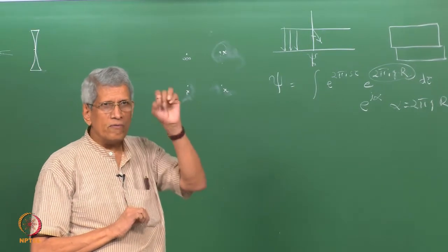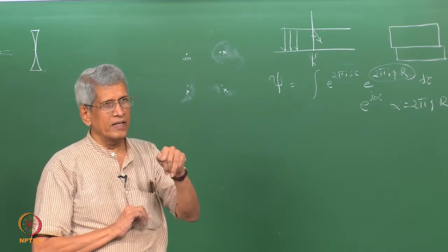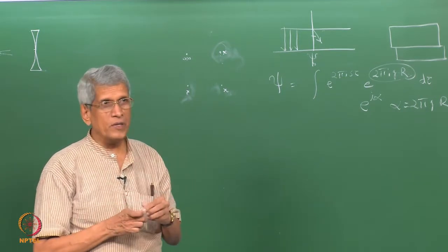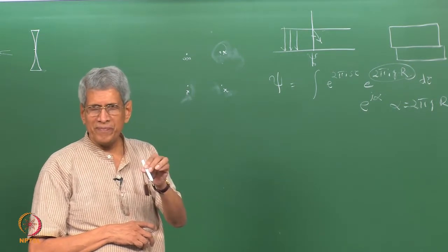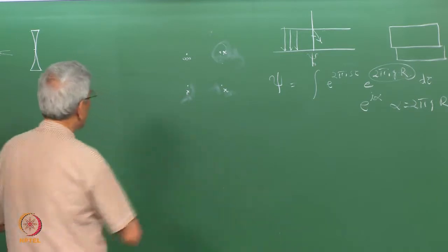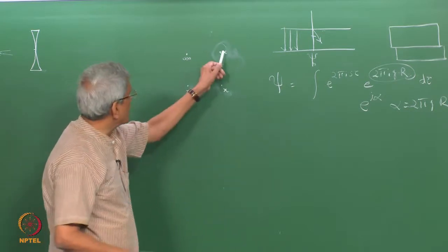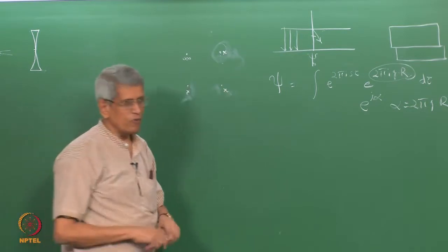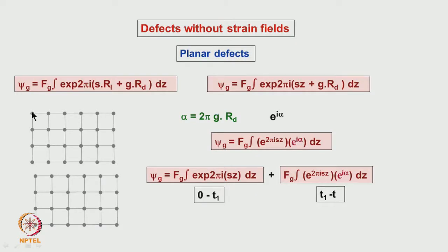But you know that when this is a strong diffraction in a zone axis, the diffracted beam also contributes to scattering in the forward direction, correct? That means the diffracted beam is now acting as an incident beam. So with this as the point, I can get another pattern corresponding to this one. Spots will come like this. Now if you draw a pattern like this, which you should do as an exercise, you will get patterns appearing here, here, here, here.